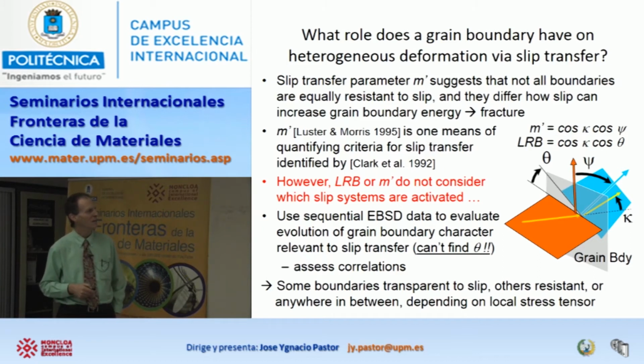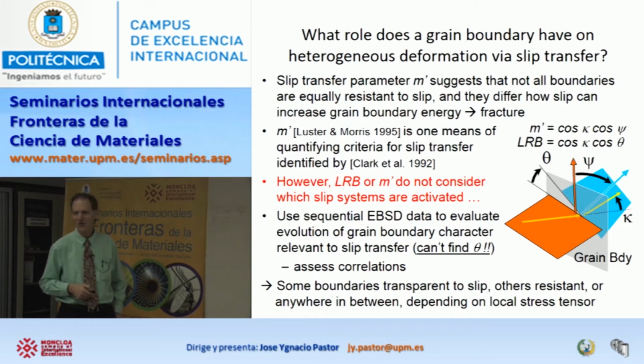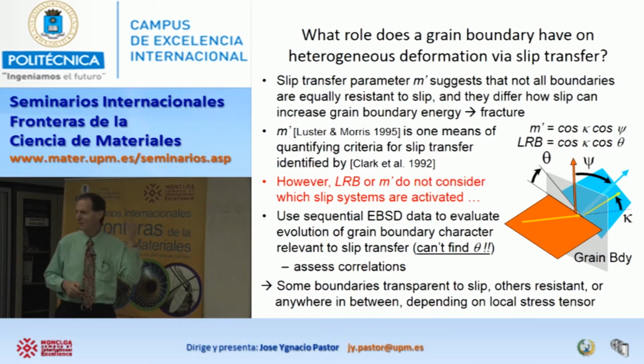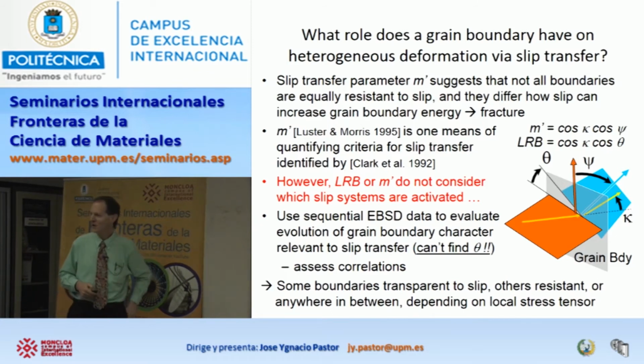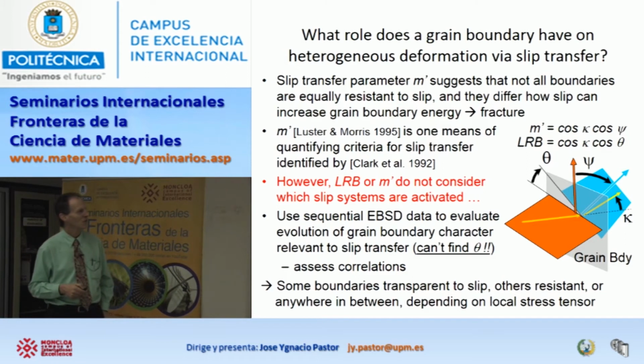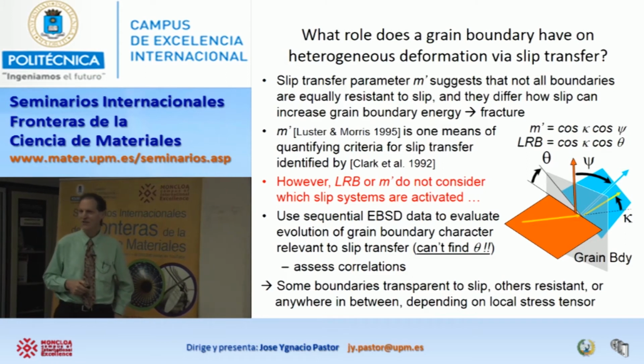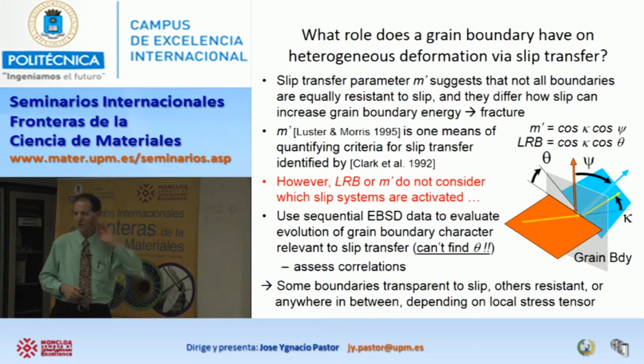And say that M prime is a parameter which says how well aligned these two slip systems are going across the grain boundary. And if the angles between these two are small, then this number becomes 1. And if this is 1, that means I have a plane on both sides where everything happens smoothly, and there's no hiccup or discontinuity at the grain boundary. So this number becomes a measure of how easily slip might pass through a grain boundary.